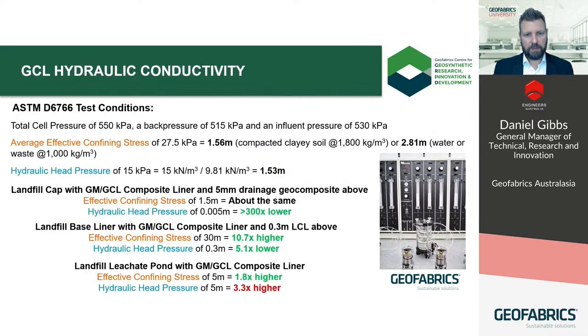We test the hydraulic performance of GCLs with deionized water to ASTM D5887 and the compatibility of many other solutions, including landfill leachates, with GCLs using ASTM D6766. These methods have specific set point values in terms of the confining and hydraulic head pressures, which interestingly were originally set with quality control in mind more so than around specific performance criteria in end-use applications.